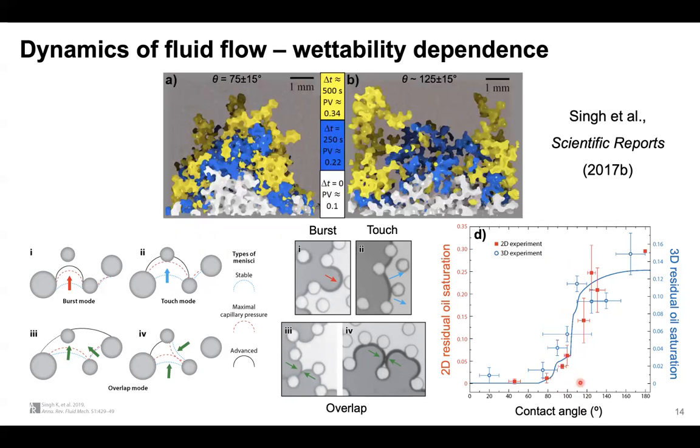And that means when, for example, we go more than 90, we move from imbibition to drainage. And in drainage, we always expect to have big bursts like Haines jumps. But in this range, we might not expect Haines jumps, but rather other instabilities like touch or overlap. Touch means when the interface moves, it sees another obstacle before jumping, or two interfaces can merge together before any jump occurs. So this sort of finding is related to sphere packs, very monodispersed packs, homogeneous porous media.